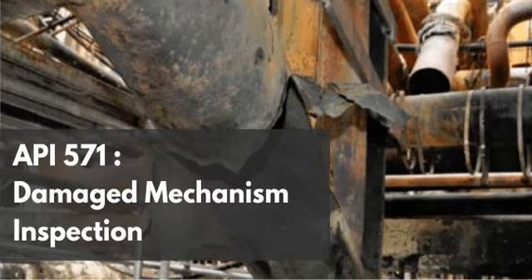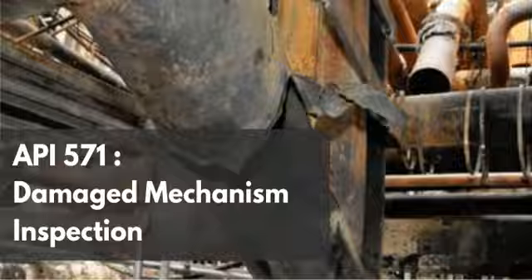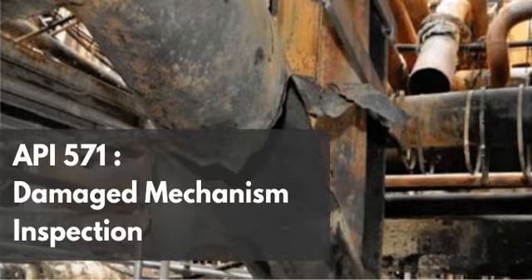First, particular attention must be paid to acid gas loading levels. What does that mean in practice? What happens if you overload the amine? It means you cannot push more CO2 into the MEA than it was chemically designed to hold. If you overload the solution, you create an excessively rich acidic environment. When that overloaded solution hits the reboiler, the thermal stress causes rapid breakdown. You must respect the chemical capacity of the amine. Got it. What's the second mandate?